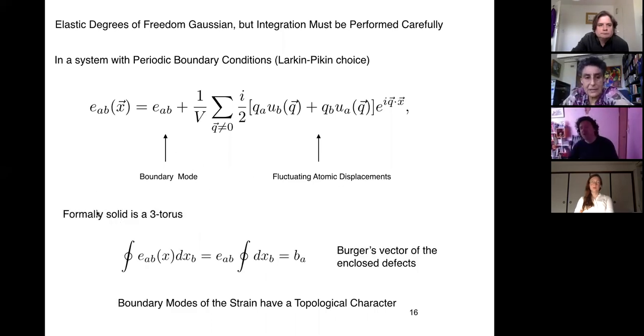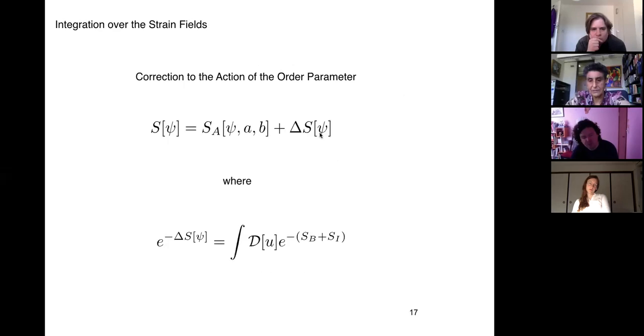Now, interestingly enough, we are formally making our solid into a 3-torus, and these boundary modes, what we can think of is that the integral over the Q equals 0 strain around a torus is going to define the number of line defects enclosed, a sort of flux. And here we can think of b_a as the Burgers vectors of the enclosed defects. So the boundary modes of the strain have a topological character. So now let's integrate over the strain fields.